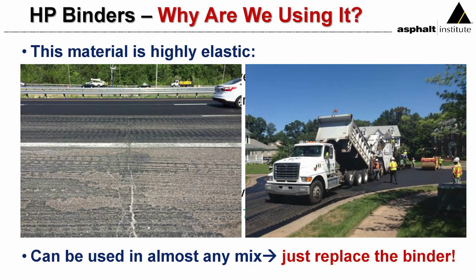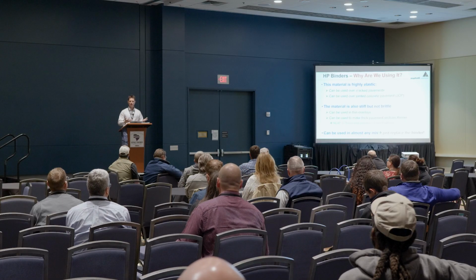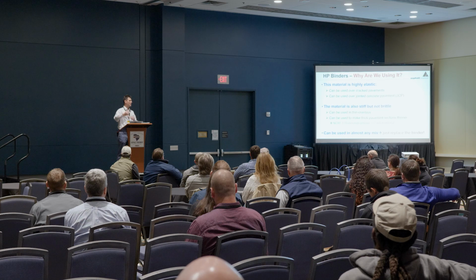So why are we using it? Again, a big application is with these cracked pavements. Now, what I say about reflection cracking is that it's not a matter of if those cracks are going to reflect back through, it's a matter of when. Whether you're using a bond breaker, some type of grid system, or high polymer, those cracks are eventually going to imprint themselves on the surface. But high polymer has been found to delay that time period by quite a bit compared to some of the alternatives. Now, it's a stiff material, but not a brittle material.